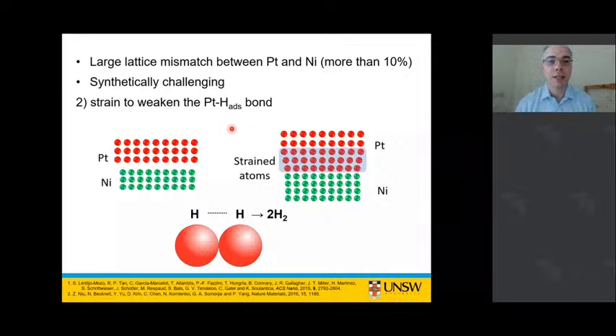It's really a very well established and well understood field. So actually there's a really large lattice mismatch. The crystal lattice, the spacing between the atoms in platinum and nickel, is actually a 10% mismatch, which is really large. And normally if you want to grow one metal on another, you need a lattice mismatch of only about 5% or lower to get your atoms to line up and join onto each other.